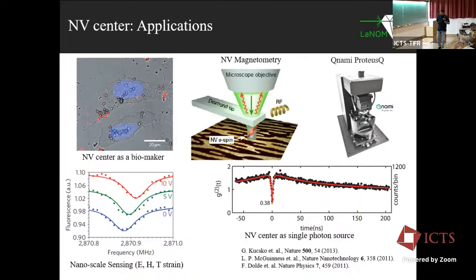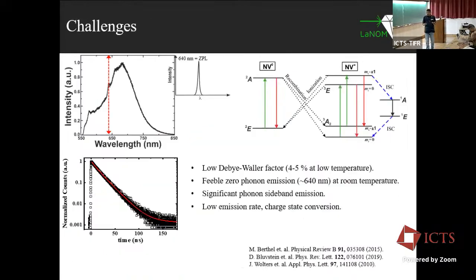So these are some of the properties, but having said all the nice things about NV centers, there are a lot of disadvantages this system has, especially from a photonics perspective. One, as I already said, is the very broad emission with a huge contribution from the phononic sidebands. We need to suppress that somehow so that you get only the pure electronic transition. And when you pump the system, there can be an ionization process, a charge state conversion. So NV minus can go to NV0, and you don't want that to happen.